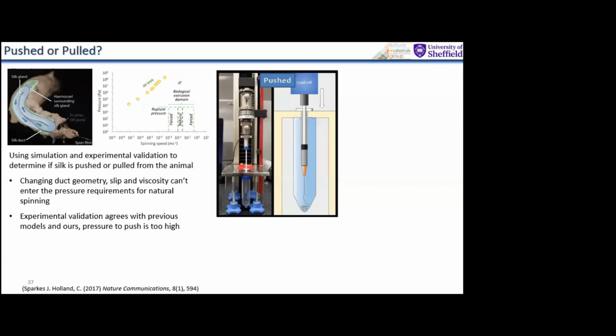And this is one of my favorite bits of a graph. We've got spinning speed in meters per second of a bit of fiber, and we have pressure on this axis. And all of our measurements and all of the theoretical calculations that are out there, you have this relationship between pressure and spinning speed. But when we look at nature, these are the natural spinning speeds. So basically, you have to put a lot of pressure into this, and it will still flow quite slowly. However, there's an upper limit known as the rupture pressure. This is literally the pressure at which the spider would pop if it should generate those forces inside it.